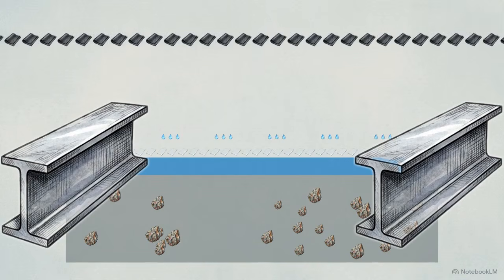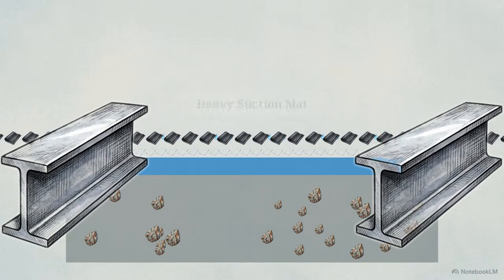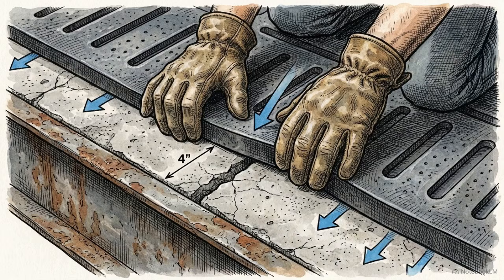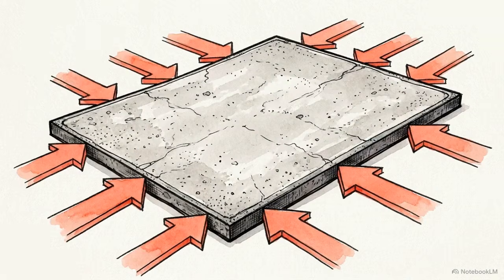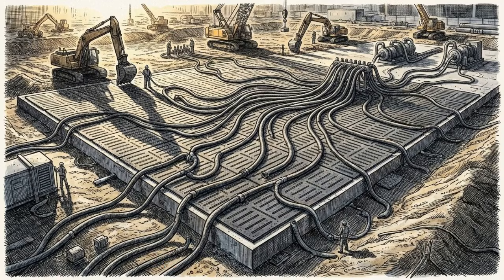Next, a heavy, impermeable suction mat is draped entirely over the filter media, covering the footprint of the pour. A 4-inch gap is carefully maintained and secured around the entire perimeter edge of this suction mat. This perimeter seal is an absolute requirement. It prevents atmospheric air from leaking under the edges and destroying the negative pressure environment needed for extraction. With the hardware in place, the open concrete slab is transformed into a hermetically sealed, vacuum containment vessel ready for fluid extraction.